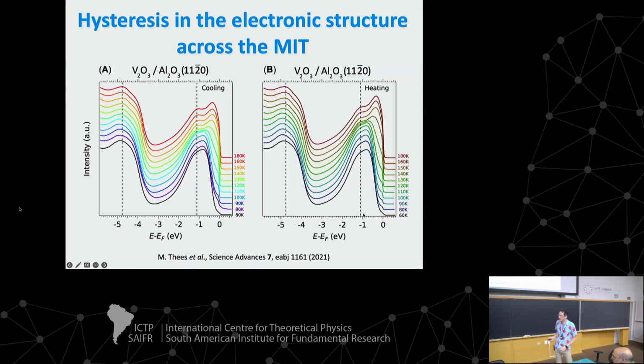If we integrate over all momenta, we can get a partial density of states, and we beautifully see how the quasi-particle peak is transferring its spectral weight to this other quasi-localized state as we cool down. And then as we warm up, the opposite trend is happening, but with a clear hysteresis between the two. We can actually fit those spectra with a simple